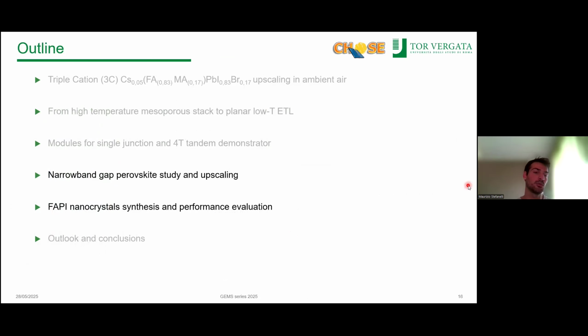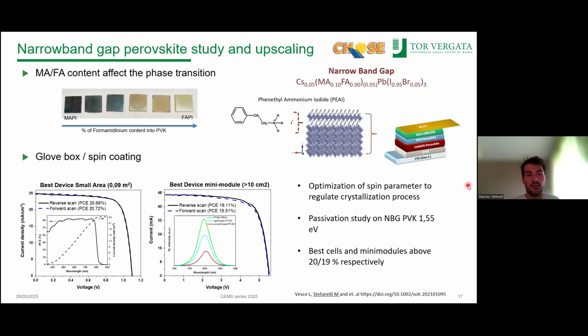After this, we moved to narrow bandgap perovskite, also because narrow bandgap became more important during this year of research. And we also evaluated the performances of this narrow bandgap perovskite from a different precursor source. So of course, it is obvious that changing the FA content in the perovskite ink affects the phase transition. MAPI is prone to give alpha phase quite easily, where FAPI is not. And for this reason, of course, we have to optimize the spin parameters and regulate the crystallization.